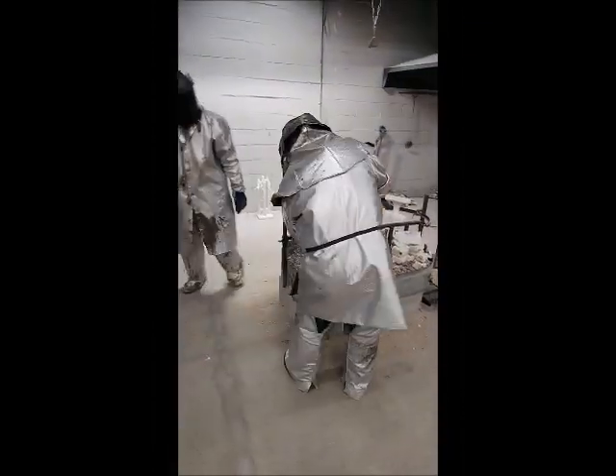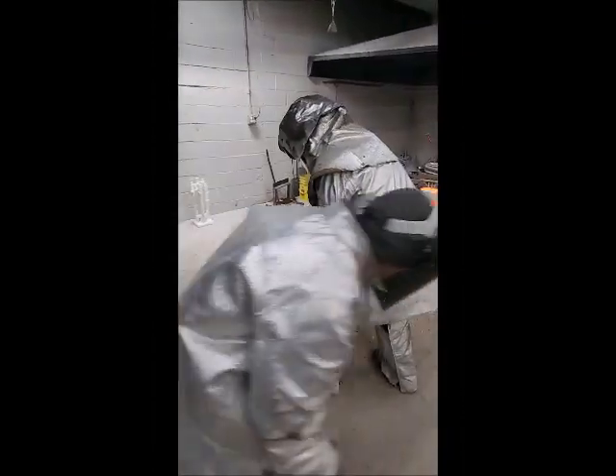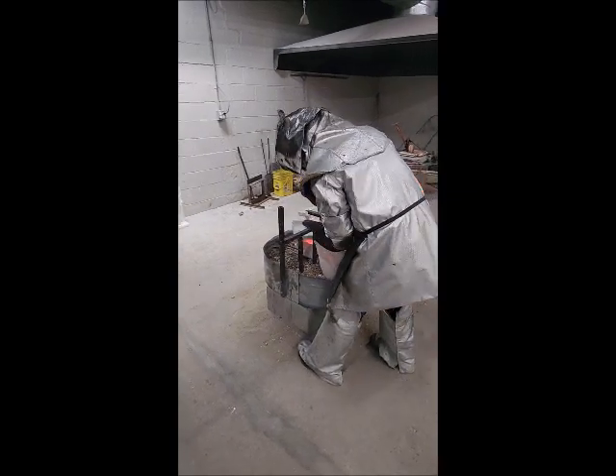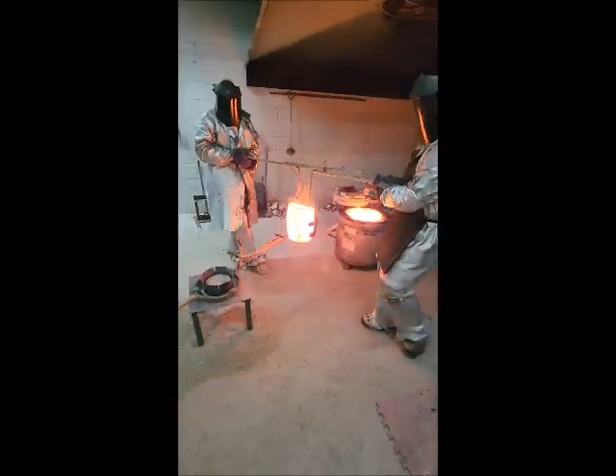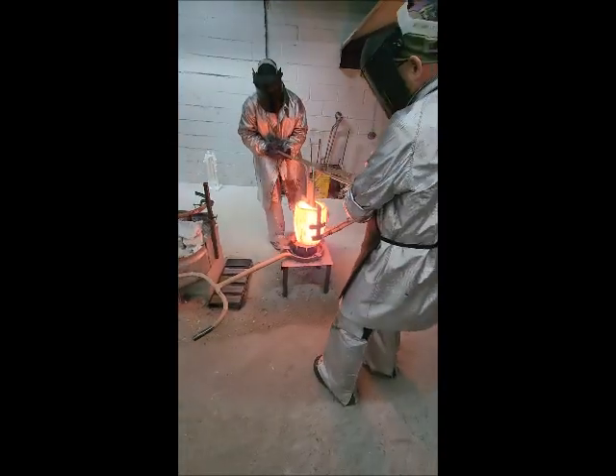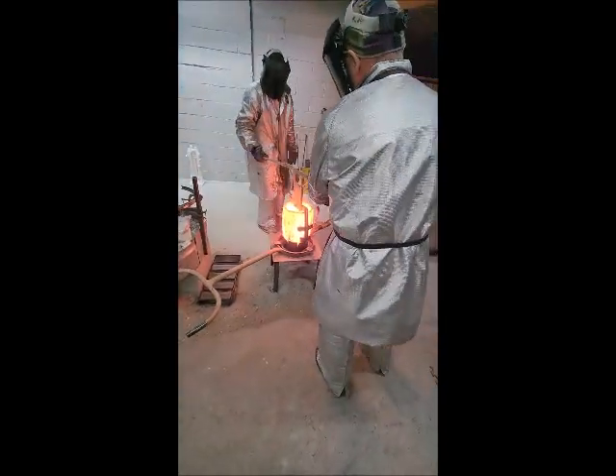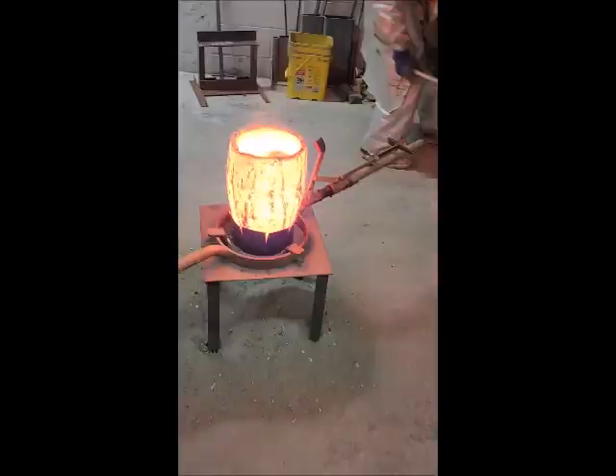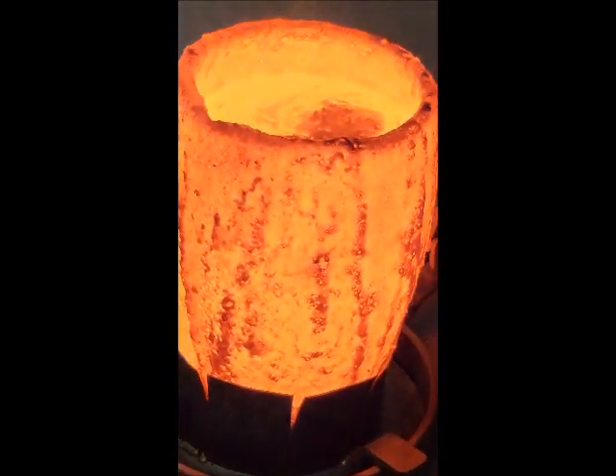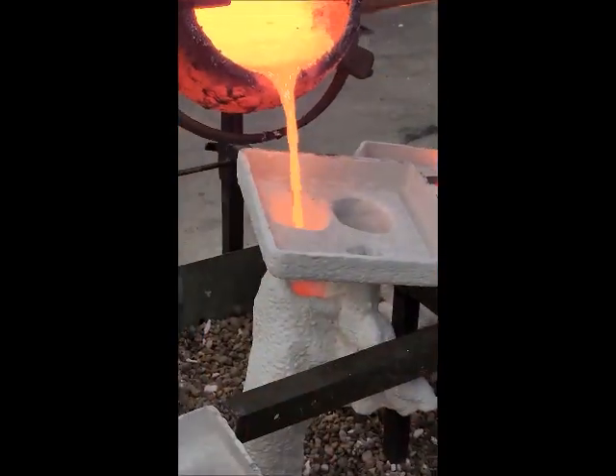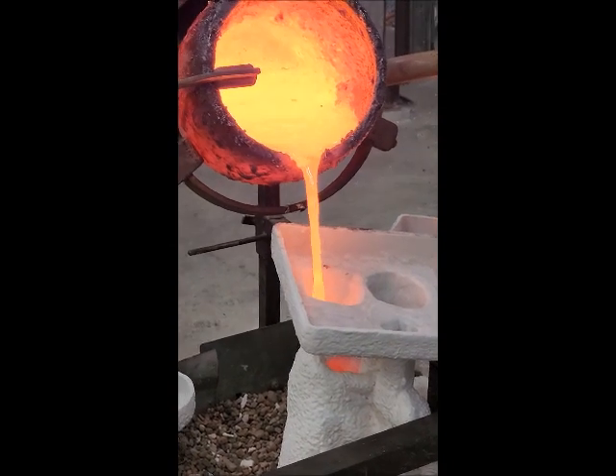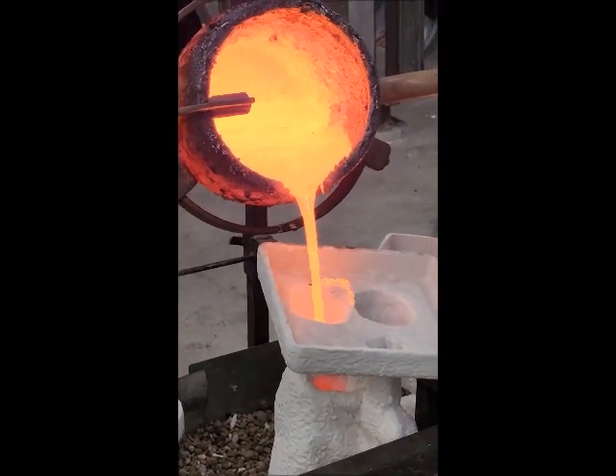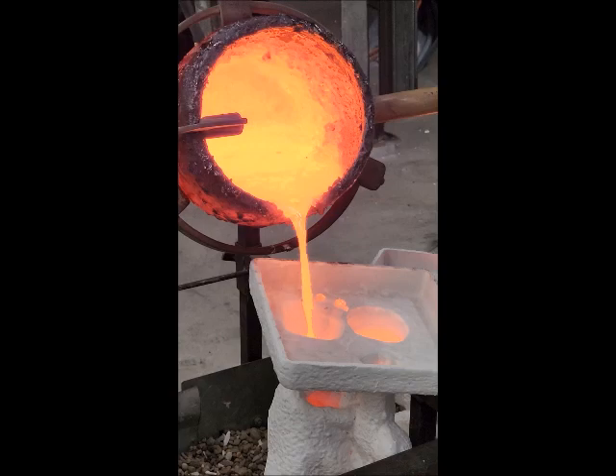Now, while the bronze is becoming molten in the melting furnace, the ceramic shell is removed from the kiln and positioned and balanced upside down in a pouring trough. The crucible, which contains molten bronze, is then removed from the melting furnace, grasped and lifted with pouring tongs, and liquid bronze is then poured into each ceramic shell investment.